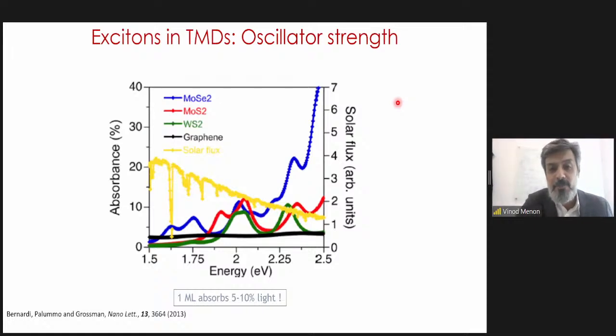Just from the standpoint of the strength of light-matter interaction, you will see that. So this is a graph taken from this paper here. The yellow line is the solar flux. So the pitch of this paper was about making solar cells, but that's not what I'm going to emphasize. What I want to point out is, let's look at one of these resonances that this material has. So in, for example, molybdenum sulfide, you will see that at around 2.1 eV, it absorbs about 12% light. So now we need to put this in context, because one layer of this material is 0.7 nanometers thick, or 7 angstroms thick. And we are saying that that thin material absorbs 12% light. That's a huge amount of light absorption cross-section that you're seeing here, compared to almost any other material that you can think of.